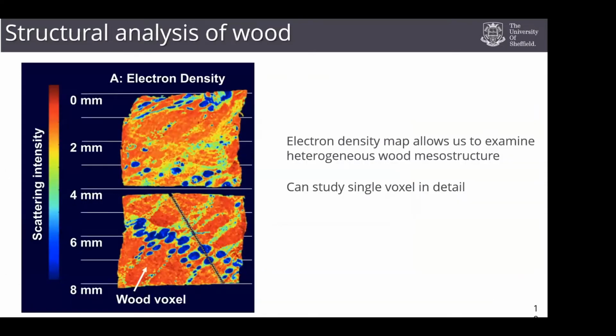So what do you get when you do these experiments? Well, here's a picture of a little piece of wood that's taken out of the Mary Rose, just bored out of the side of the ship. That's the top of the wood that would have faced out into the sea. And then this is a piece of wood going in about 8 millimeters into the depth of the hull itself. And this is just showing you an electron density map, and that just allows us to look at the mesostructure of the wood. And what we can tell is, in these red regions, these are pretty dense. And then in these blue circular regions, this is where you've got pores that are present in the wood. This strange looking line is an artifact from how we put the data together.